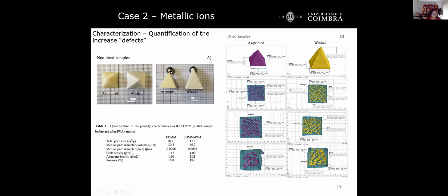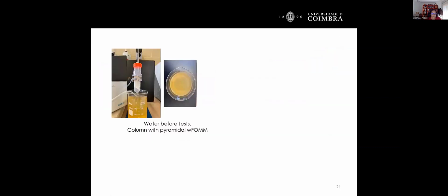So the total pore area increased when you remove PVA. The median pore diameter also increased when you consider all the pores in volume. When you consider the diameters in area, it also increased. The bulk density decreases, the apparent density decreases, and of course, the percentage of porosity increases. So here we demonstrate that, in fact, it's not just us saying that we have an increase in defects, in this case porosity, okay? So we printed the pyramids, we made it like a test column, and we had this beautiful water on a Monday morning, and we started to make our tests.